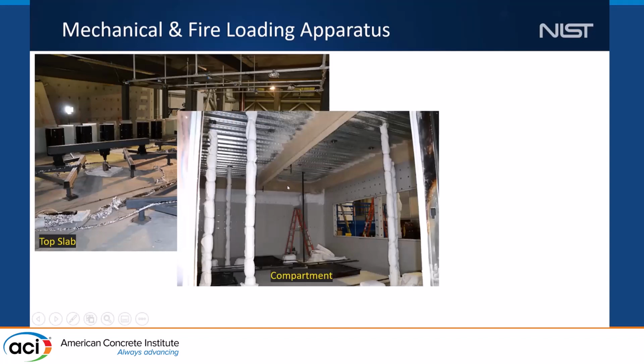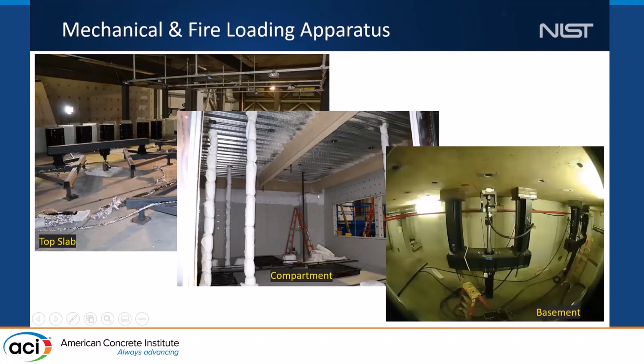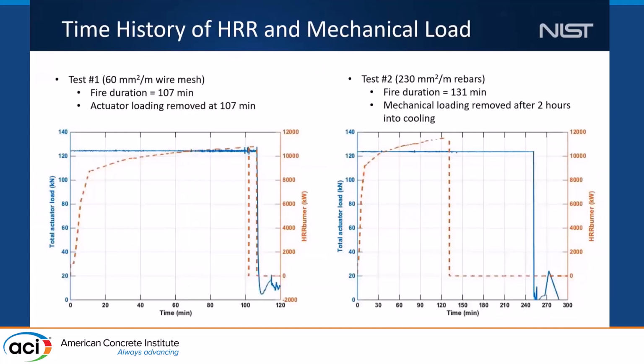And this is the test compartment underneath the floor slab. Basically, we used these natural gas burners that create the intense fire condition underneath the test floor slab. And then this vertical line is nothing but the water-cooled loading tubes that connect between the loading frame at the top of the slab and the actuators at the basement. In that way, we can actually create mechanical and fire loading simultaneously.